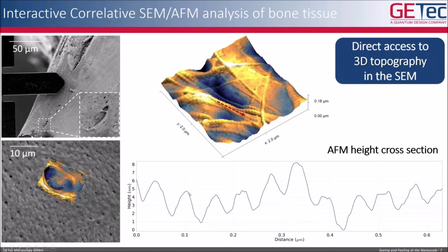We can easily observe this height change even inside the SEM with all the running turbo pumps and all the mechanical vibrations. So the noise level that we can achieve with our system in a standard SEM is around 200 picometers. So we can really get to atomic resolution in Z with the AFM inside an SEM or dual beam system.